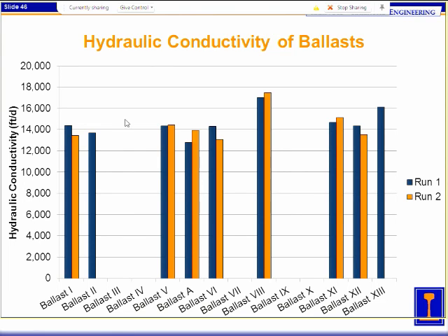We're seeing very high flow rates, which we expect. In the ranges of, I think our lowest one we've run is not on here because it was not one of the first tests we ran, but it was around 11,000 feet per day. Highest we've tested is up at about the 17,000 mark or so.